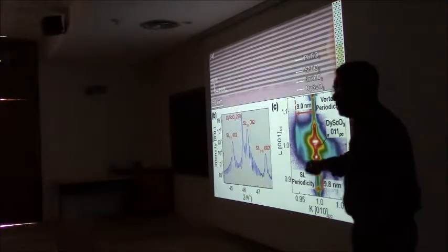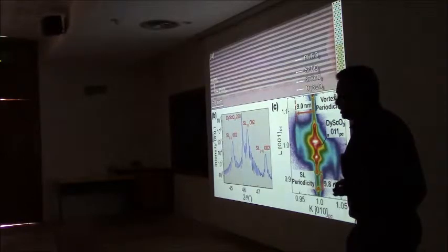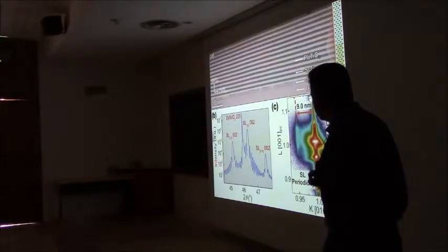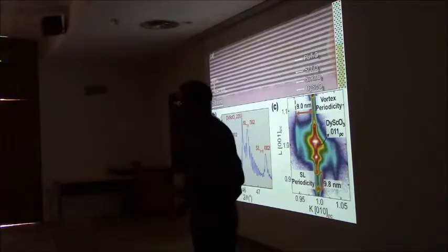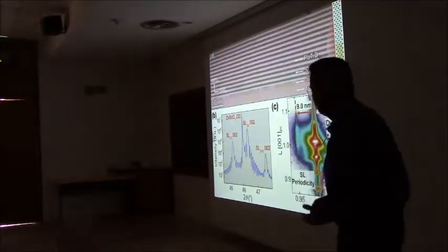I'm going to go deep into this in the next few slides, so we will see a lot of electron microscopy data. X-ray diffraction, this looks pretty standard. You can see very clearly the superlattice peaks. And you can see also those oscillations, which is telling you that these layers are very coherent. They're not interdiffusing. Already it's telling you something is very, very high quality.